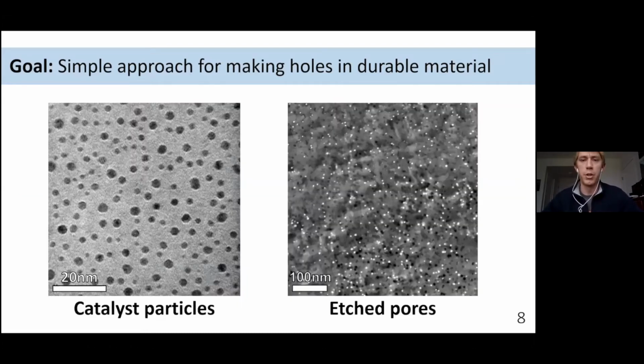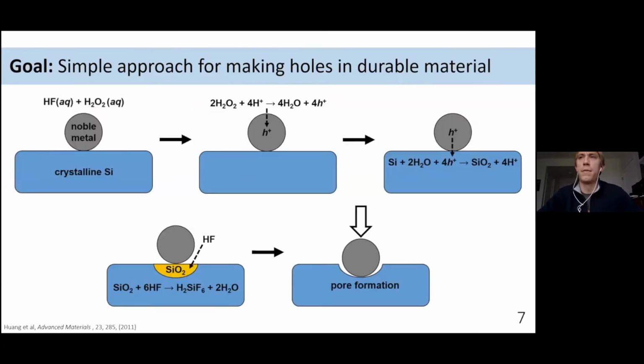And then most of our innovation, I should say, over the last 4 years has been really innovating around the catalyst deposition and form factor of that catalyst to make it as small as possible, as dense as possible on the silicon surface, and then allow it to sink as deeply as possible, preferably through a thick silicon slab that can then act as our membrane filter.